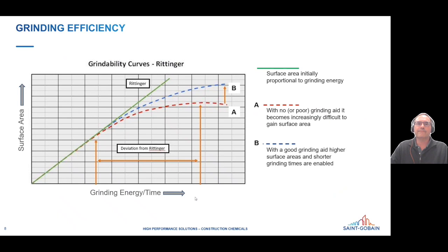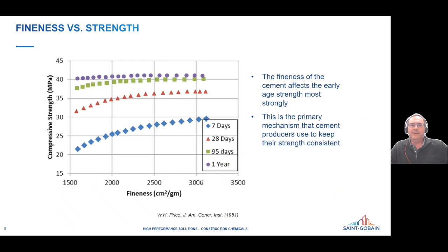So it's good to then take a step back and remember why we're grinding the cement to a relatively high fineness. If you want to get good compressive strength development, particularly at early times, you do need to have a fine cement. As this data shows here, this is some older data from 1951, but it's showing that at a relatively young age, now 7 days is really not that early, but it's the earliest time shown here. At early times, when you have a low fineness, the compressive strength is much lower than it is when you have a higher fineness. Now it's showing at later times, it doesn't make as much difference. But of course, you can imagine as we come to earlier times, like one day, this relationship is going to be even stronger. So you really do need to grind the cement fine, particularly to get the early strength.